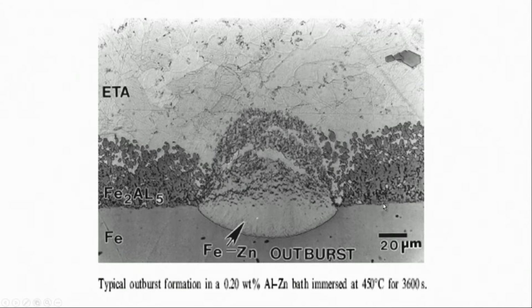As I mentioned, this phase reduces the kinetics of Fe zinc intermetallic formation, but as the aluminum content is quite low, if you do not control the time carefully, you will see that there is failure of the coating to a very large extent. This is called outburst formation. Outburst formation is one of the biggest troubles associated with galvanizing where you have a very low percentage of aluminum, in this case 0.2%.